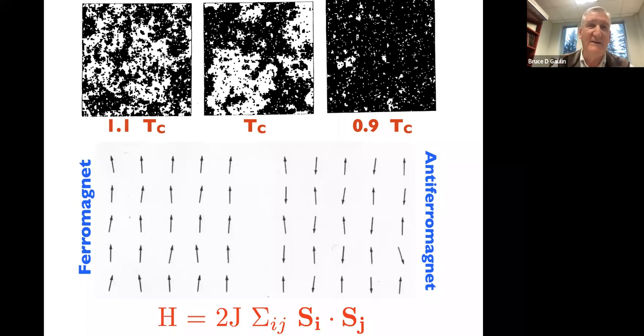If you're at sufficiently high temperatures, entropy dominates and the system's very disordered. But you still get small regions of correlated up spins coexisting with similar regions of correlated down spins. The regions of correlated spins get smaller and smaller as you move up to high temperatures. At low temperatures, the system is in an energy-dominated long-range ordered state, where you might have some of the minority spin state, the down spins, the white squares, but it occupies a pretty small volume fraction of the overall material, so mostly you've got a sea of up spins and a small number of down spins, and as you go to lower and lower temperatures, the volume fraction of the down spins would go away.